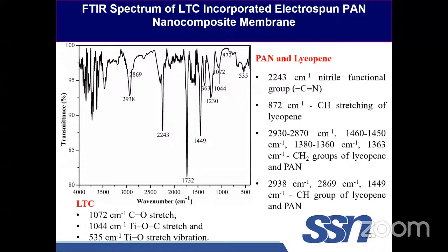Later on, we studied the FTIR spectra of the prepared nanofibers. 2243 gives us the nitrile group, C triple bond N functional group, and the peak at 872 gives CH stretching of lycopene. 2930, 2870, and 1460, 1450, and 1380, 1360, and 1363 correspond to the CH2 group of lycopene and PAN, and 2938 and 2869 and 1449 correspond to the CH group of lycopene and PAN. CO stretching is seen at 1072, Ti-O-C stretch is seen at 1044, and Ti-O stretch is seen at 535.